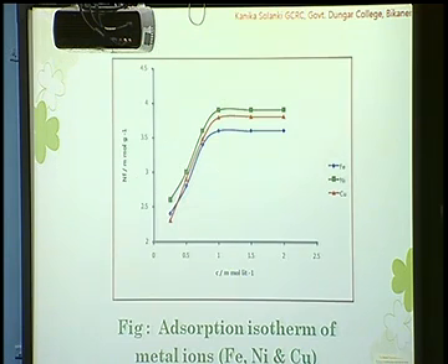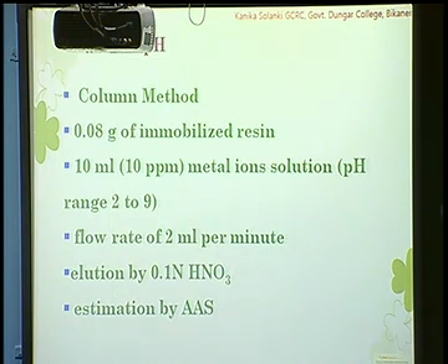Adsorption isotherm values are also given. Now, this is the graphical representation of adsorption isotherm of ferrous, nickel, and copper. The effect of pH. To investigate the effect of pH, we used the column method, and the flow rate was maintained at 2 ml per minute, and elution was carried out by 0.1 normal HNO3, and the estimation by AAS.